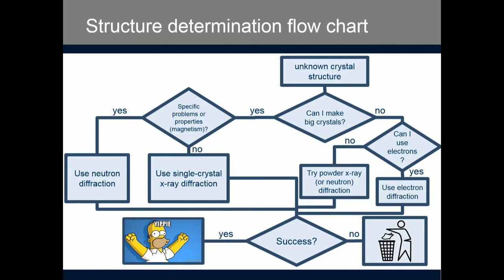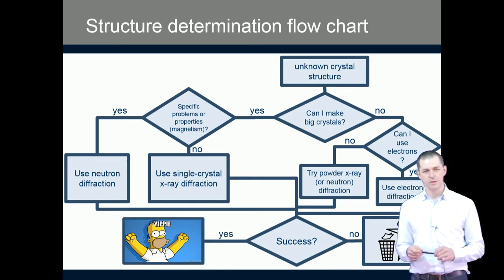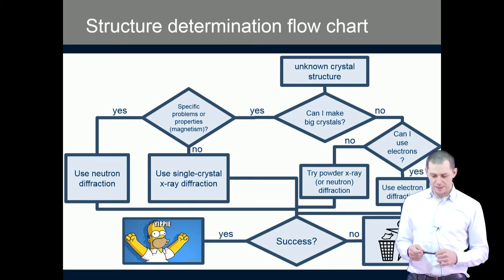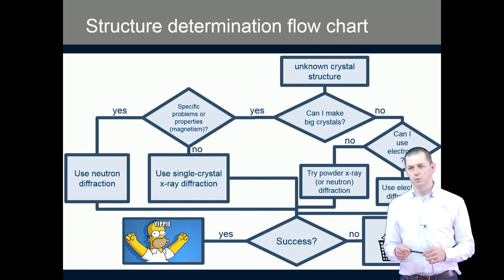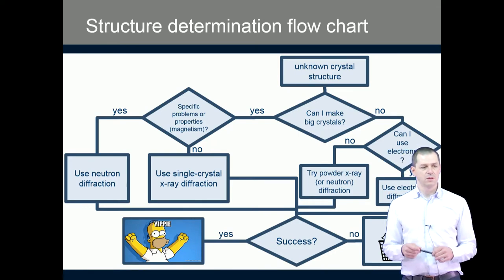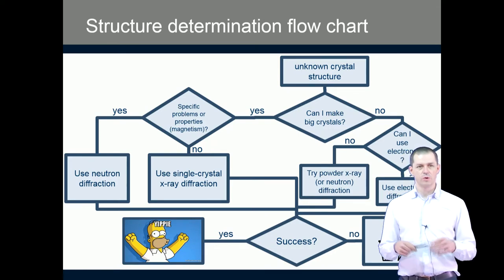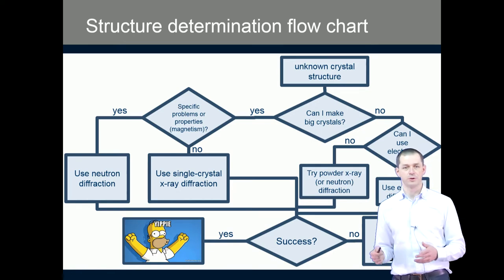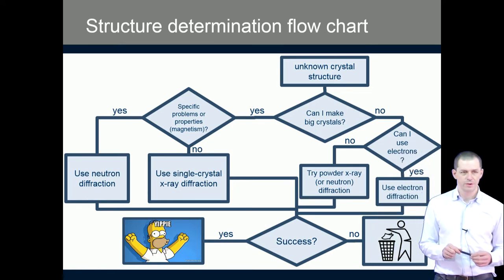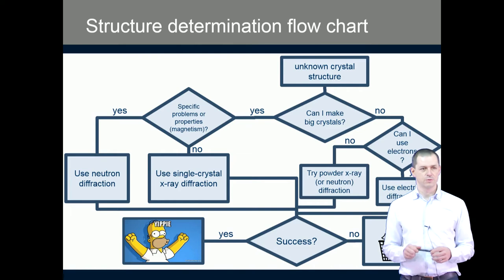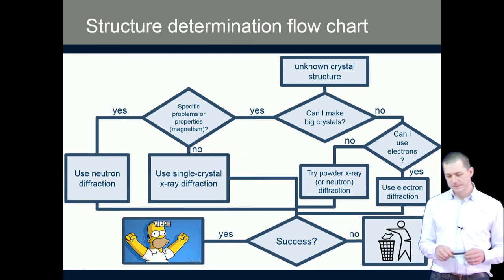The cases where you cannot use electron diffraction are maybe various. One of them is that the material is not sufficiently stable in the electron beam. Another case can be that you need to use some environmental, non-ambient conditions, like high pressure. So if you want to do high pressure, powder diffraction, electron diffraction will not help you.